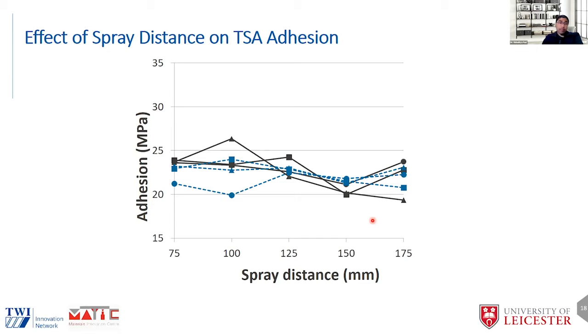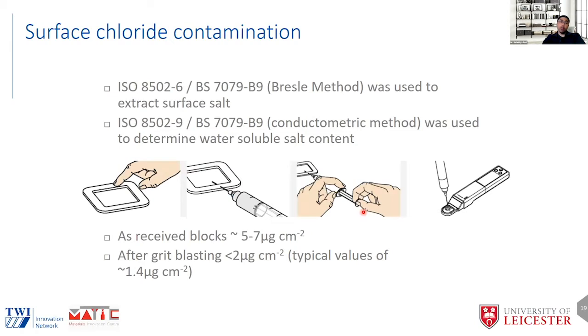In terms of other factors related to surface prep, one of the things people worry about a lot is surface chloride contamination. We looked at this in fair bit of detail a few years ago, using one of the ISO 8502 standards to look at the effect of surface salt contamination. As-received blocks of steel had about 5 to 7 micrograms per centimeter square. We grit blasted it to Sa 3, and we had typical values of about 1 to 2 micrograms per centimeter square.